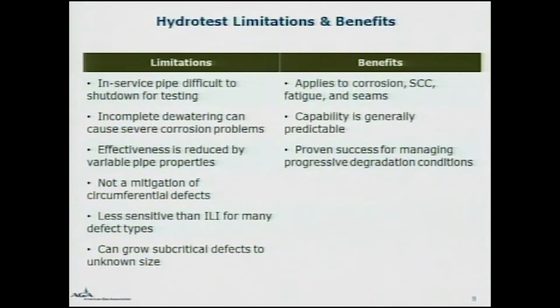It should be pointed out that a hydrostatic pressure test has no predictive value. It is a snapshot in time, and there is no data available for other defects which may exist. It finds the weak link defect which fails below the test pressure. There is also the possibility that a hydrostatic pressure test can cause subcritical defects to grow and possibly fail upon subsequent pressurization at a level below that of the first test, in a phenomenon previously referred to by Mr. Mayberry as a pressure reversal.